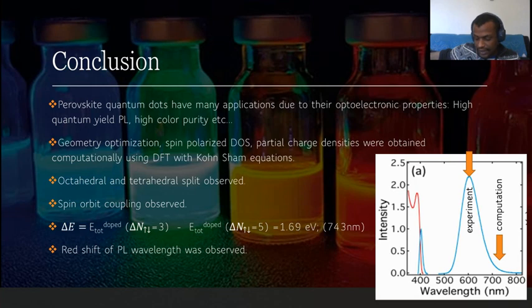It's because it adds stability that the perovskite quantum dot didn't have without doping, and also to allow for, you mean optical stability? Yes, optical stability, and also to allow for a change of the band gap to allow the change of the emission as well. Because I understand that with changing size, the PL, or the photoluminescence, can change, but then we reach a band gap limit, so we need doping to allow for further changes.